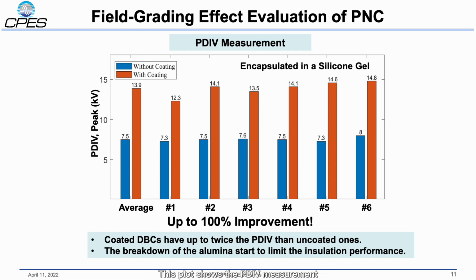This plot shows the PDIV measurement results of those samples. For the samples with the coating, they have clearly much higher PDIV than the samples without coating. Coated DBCs have up to twice the PDIV of uncoated ones. And actually, during the test, we started to see some breakdown inside the alumina before the encapsulation failure, which means the alumina starts to limit the insulation performance instead of the silicone gel, which is usually the bottleneck of the insulation for medium voltage power modules.